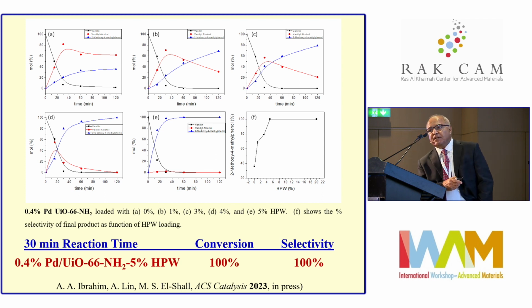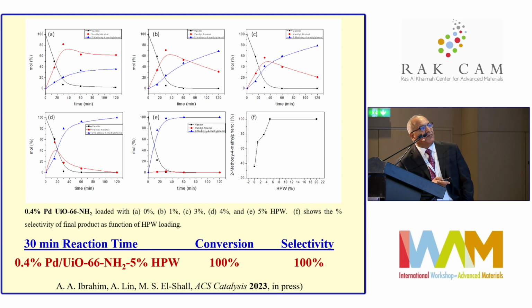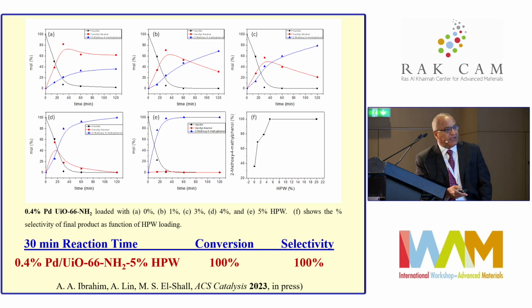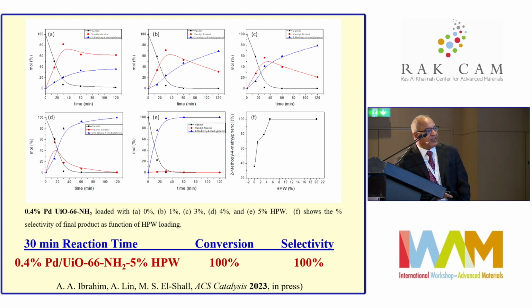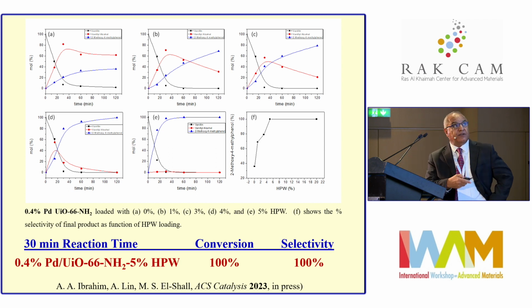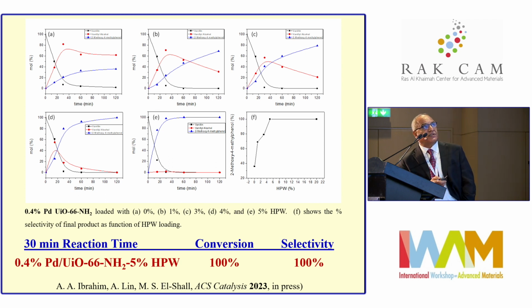The important point here, as compared to the UiO66 MOF, is that with the incorporation of HPW, the solid acid, we are able now to reduce the concentration of palladium catalyst from 2% to 0.4%. So this is a significant reduction of the amount of palladium used, and with 0.4% palladium, we can reach 100% conversion within 30 minutes reaction time, with we can say 100% selectivity for the desired product, which is methoxyphenol.